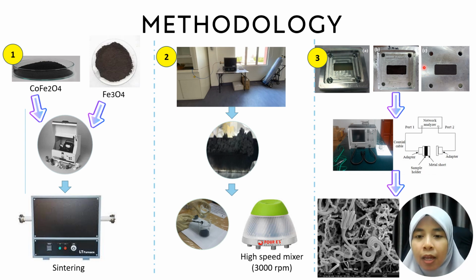For example, X band frequency range from 8 to 12 GHz and Ku band frequency range, which is from 12 to 18 GHz. And then we measure the microwave characterization of the sample by using vector network analyzer. So this is the important equipment in order for us to know the reflection loss of the materials.